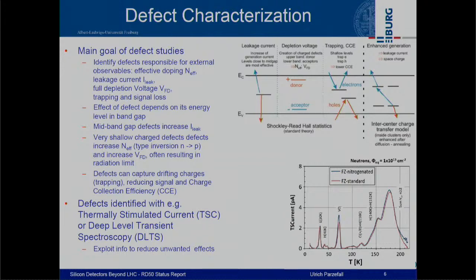Another group of defects, particularly limiting at very high radiation doses, is trapping. You have states that can trap a signal charge in your detector and keep it for a while before releasing it, which reduces the signal available, giving lower charge collection efficiency, lower signal in the detector, and ultimately lower detector performance.